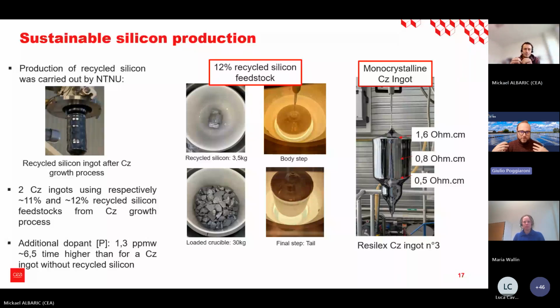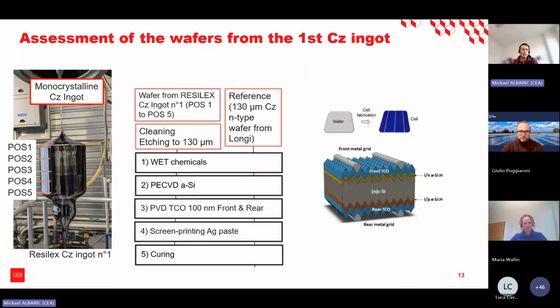Can you disclose something about the tests that you are going to make with the cells produced out of this ingot? I mean, how long these tests are going to be carried out? I would say that the first test will be, I think we are going to reproduce exactly this. We are going to take wafers on 5 positions from the top to the bottom. It's really important to do this because due to the segregation, the quality of the wafers at the top is different from the one at the bottom. So it's important to have this evolution across the ingot.